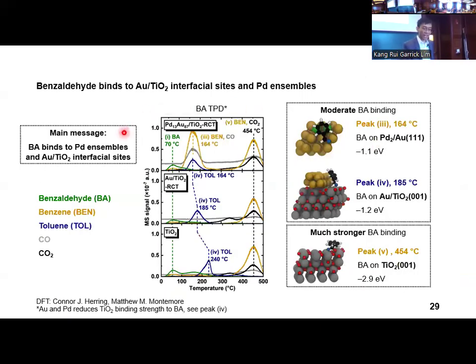To elucidate the underlying mechanism behind the support and embedding effects, we performed benzaldehyde temperature programmed desorption in combination with DFT calculations to investigate how benzaldehyde binds to the surface sites. I will not go into the details, but state our main finding that benzaldehyde binds to the palladium ensembles and the gold titanium interfacial sites.